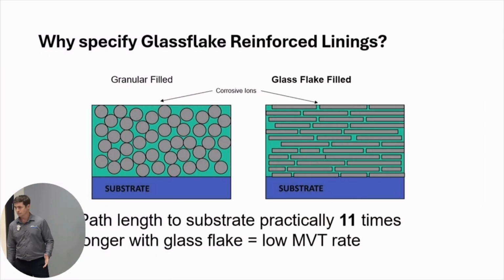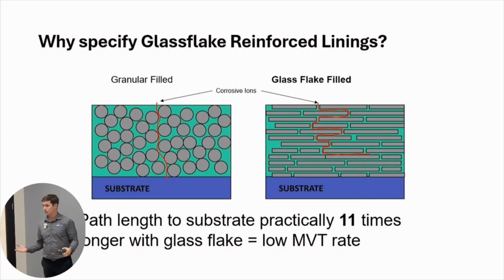We do that. Corrocoat is based on glass-flake technology. In the early 50s, the founder of Corrocoat, while he was still working his regular job, started tinkering around with resins and glass flakes in his garage until he found a formulation that he liked. The idea is that if you put glass flakes in a coating and you load them correctly, and you add other additives and fillers to ensure that you get the viscosity right, you can make a situation where the corrosion-causing ions go into a tortuous path.